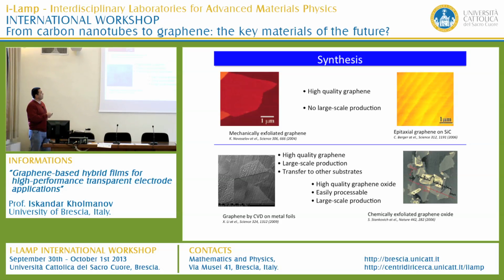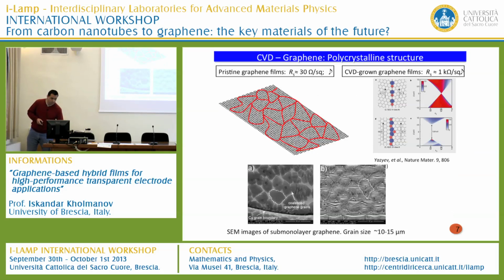This gives very high quality graphene, but the problem is that they cannot produce large quantities of graphene. The other 2 methods are CVD grown graphene on metal surface, which was first developed by our group, by Ruoff's group at UT Austin, and a wet chemistry method that produces not exactly graphene, but chemically modified graphene or graphene oxide. We worked mainly on two types of graphene: one is CVD grown graphene, the other is graphene oxide.